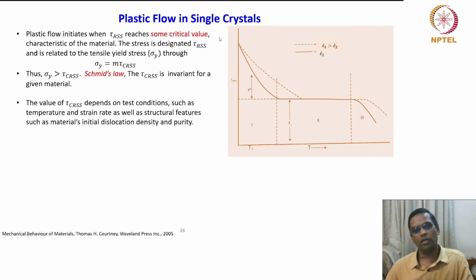Here is an important plot that we need to keep in mind with regard to the critical resolved shear stress. The critical resolved shear stress is plotted against temperature, a tau CRSS versus T plot. You can see that it is not only showing the temperature variable, there is also a strain rate variable. The dashed line is epsilon 1 dot, which is greater than epsilon 2 dot, and the solid line is epsilon 2 dot. So it shows both effects, the temperature effect as well as the strain rate effect.